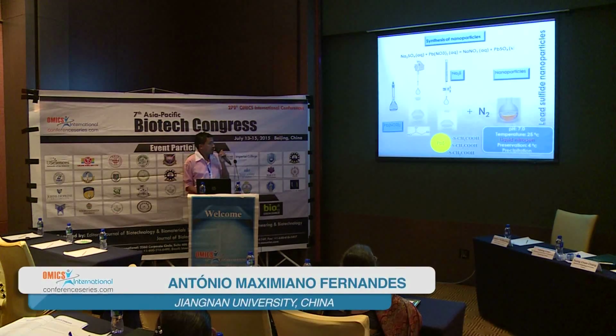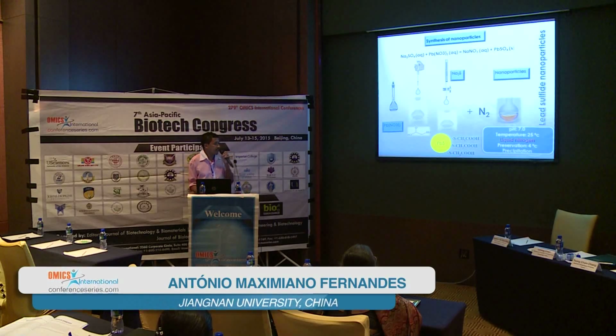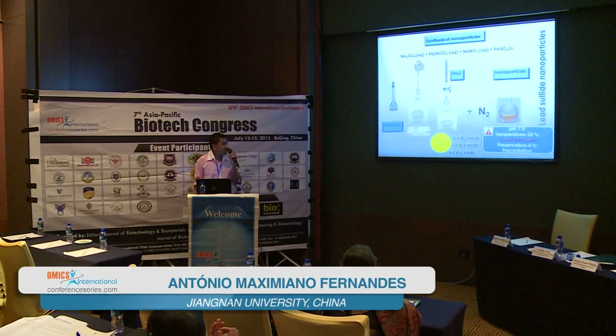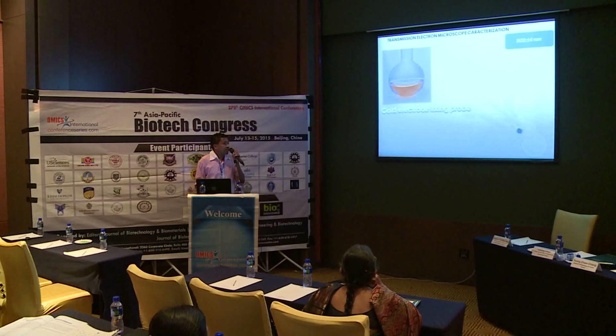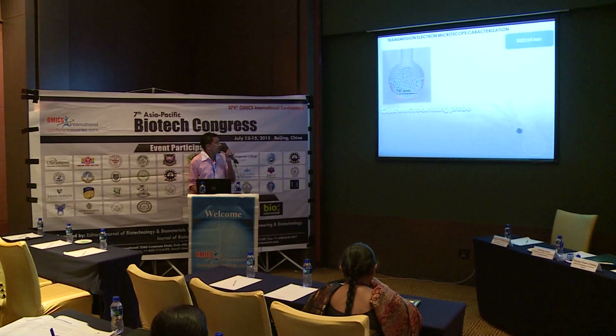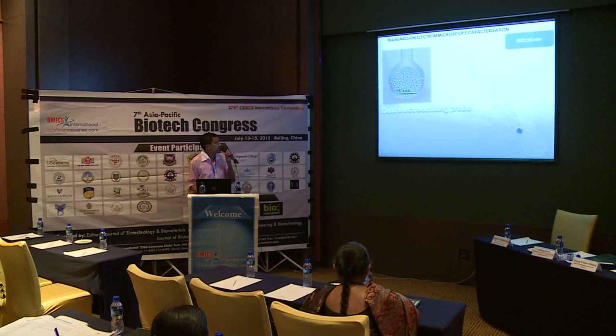And we use the acid group to cover our nanoparticles. But you should pay attention to the pH, the temperature, the liquid nitrogen, the preservation, because it can cause some problems during precipitation. So this is our nanoparticles. It's like lead sulfide colloid. This is the good quality one. This is the transmission microscope image.